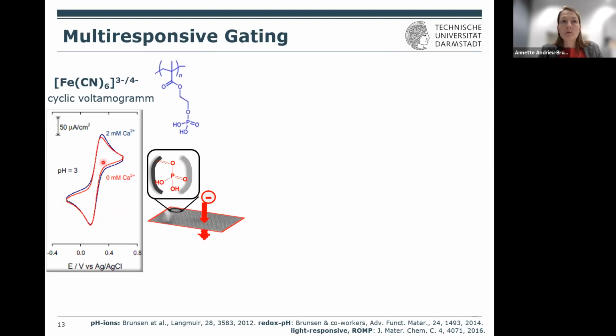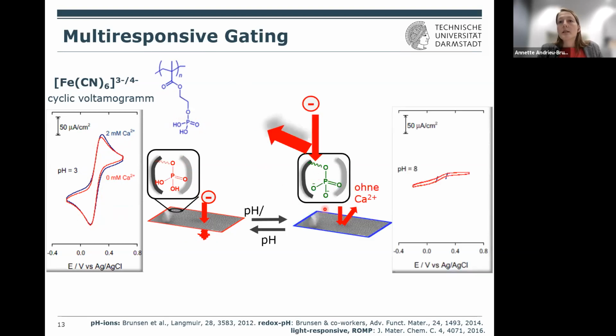So this indicates transport is possible, and you can even get information on the concentration of the redox active probe molecule. In this example, of course, it's obvious that you can just change the pH, so the polymer becomes negatively charged, and what you would expect intuitively is that the pores get electrostatically closed. This is because the pore size is in the range of the Debye screening length. I hope everybody somehow knows what this means. So basically, the distance that the molecules feel the electrostatic interaction is larger or in the same size range as the pore diameter. So this means that when the charged molecule arrives, and it's getting in contact with a negatively charged pore, of course, it doesn't like to enter due to electrostatic repulsion. And this is then reflected in a decrease of the IP in the cyclic voltammogram as the molecule does not arrive at the electrode anymore.